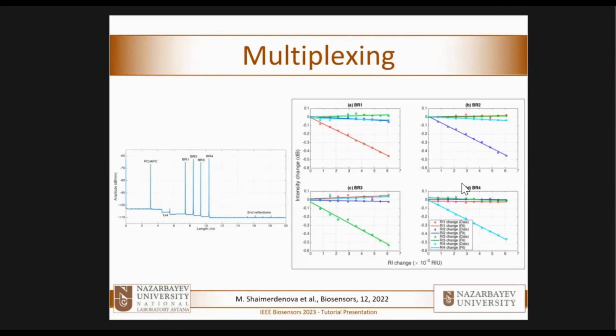But each one of them appears in a different part of the fiber. So we have here a network of splitters that you can simply close into a box that has a different length for each of the fibers, such that each of the sensors appears in different parts. So basically we introduce a delay line in each of the elements, and it works. So now we don't have just one sensor, but we have 4 sensors operating simultaneously. As I said, we have done in our lab up to 16. But virtually, considering that our analyzer can go up to 32 meters, and the sensors need to be spaced by 20, 30 centimeters at max, or more, you can calculate that hundreds of sensors are virtually possible. And as you can see, each sensor detects separately with minimal crosstalk.